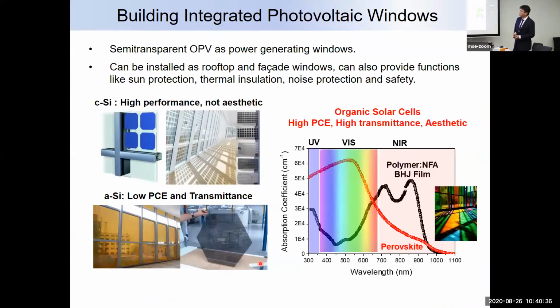And compared to inorganic material, a very unique property of organic material is its tunable absorption properties. If you look here, this is one of the absorption profiles with the bulk heterojunction. We can selectively tune the absorption in the infrared, allowing the visible light to pass through more easily. These intrinsic absorption properties make it very unique compared to inorganic material, which has a continuous band and always has a very strong absorption in the visible range, but low absorption in the infrared range. So now we can imagine that we can harvest the infrared light and then make a highly transparent device.